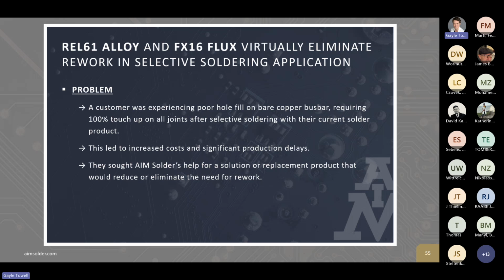So here's an example with a selective soldering application. In this case, they were having poor hole fill on a bare copper, requiring they had to touch up 100% of the joints after the selective soldering, which, as you can imagine, really slows down your production line. So significant costs, significant production delays, and they needed a solution.